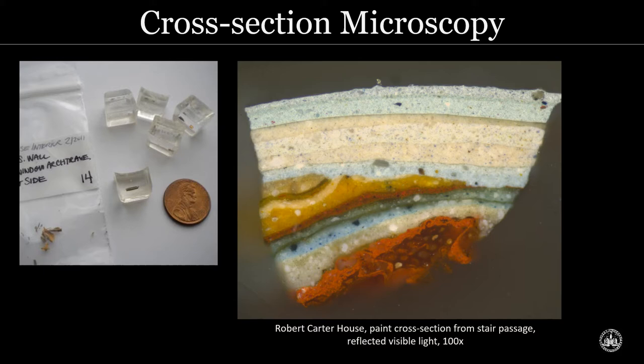So to conduct this technique, samples are collected on site with a surgical scalpel, and they ideally contain a portion of the substrate, usually wood, with all of the paint layers attached. And then back in the lab, these paint chips are mounted in a small cube of polyester resin. And once that resin cures, the cube is ground down until the edge of the paint chip is exposed, and the surface is then polished to a mirror smooth finish and examined with our high-powered microscope. And in my lab, I use a Nikon Ni-U microscope.